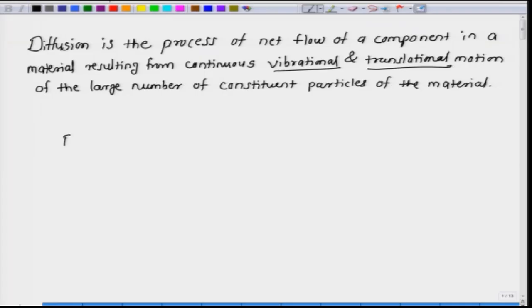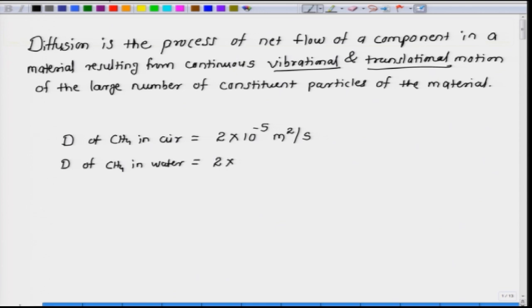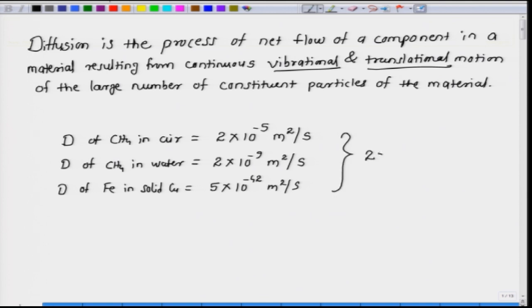As an example, let us compare the various diffusivities in different media. The diffusivity of methane in air is around 2 times 10 to the power minus 5 meter square per second. The diffusivity of methane in water is around 10 to the power minus 9 meter square per second. And if you look at the diffusivity of, let us say, iron in solid copper, you will find it is around 10 to the power minus 42 meter square per second. All these values are at 298 Kelvin.